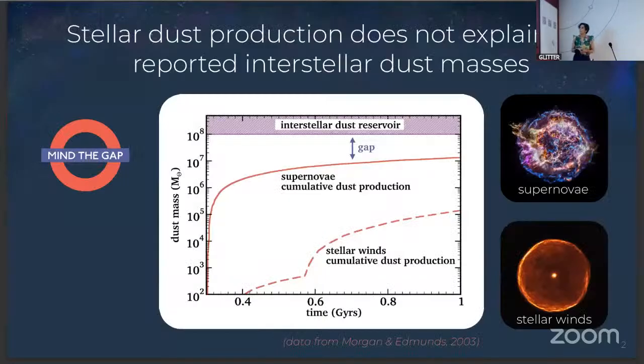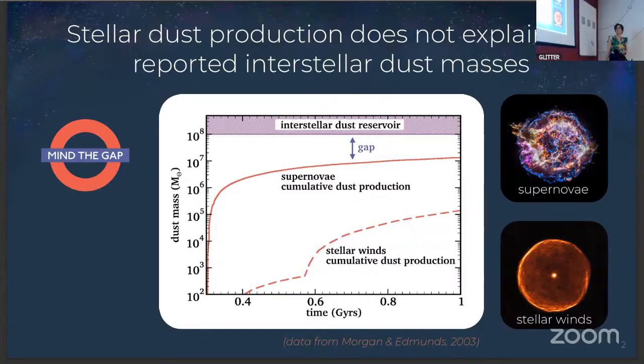Okay, so now why is it interesting to actually detect nanosilicates? Well, the problem is that if you look on a galactic scale at the interstellar dust reservoir, which has a certain value. So, for instance, if you look at the high redshift universe, we find that there are some galaxies that have 10 to the 8 or 10 to the 9 solar masses of dust in them. This has been detected in submillimeter thermal emission from the dust.